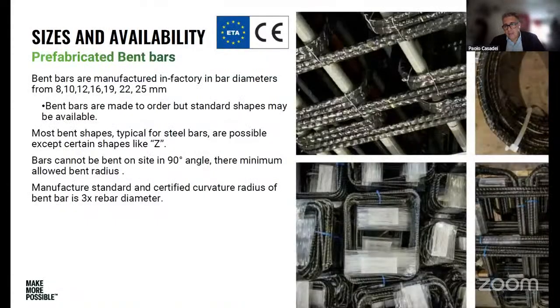We can also supply bent bars, and that's something you have to be aware of. This is probably, I would say, not the bottleneck, but certainly something that is slowing the adoption of this material, and I really want to be very open and transparent on this. Straight bars, if you remember what I told you before, remain straight and cannot be bent like it happens with steel. So when we build something with GFRP, we need to supply stirrups or any bent shape, like you see them here in the picture, already pre-shaped. Why? Because the resin is a thermoset, so it cannot be bent and deformed locally. It has to be pre-formed at the factory.